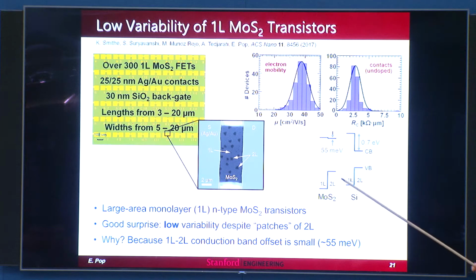It turns out that if you have monolayer, bilayer regions, the conduction band offset is only about 55 meV. We were not the first people to point this out. We found a few papers before us who pointed this out as well. But I think we were the first to point out that in the conduction band, this means that the electrons don't really see these energy sort of barriers, right? Because this is 2 kT. So it's kind of a small scattering potential if you think about it.